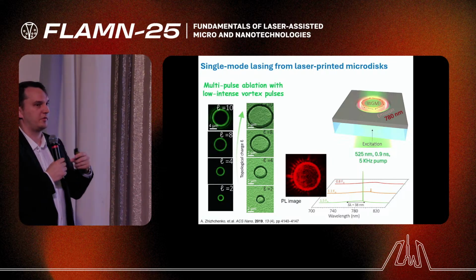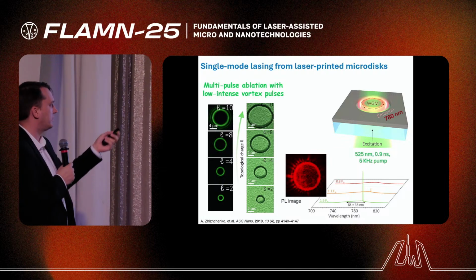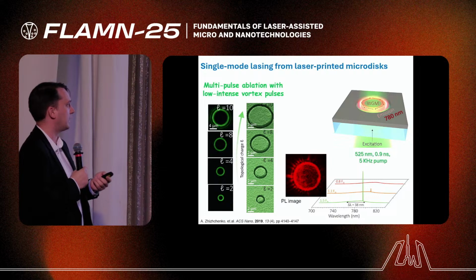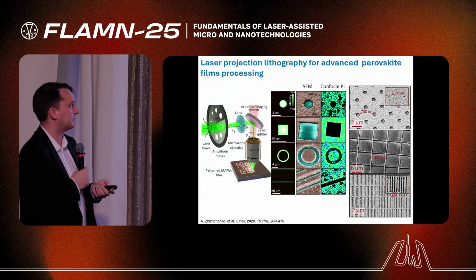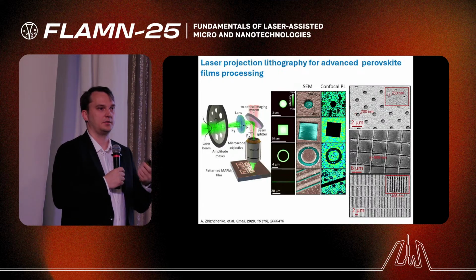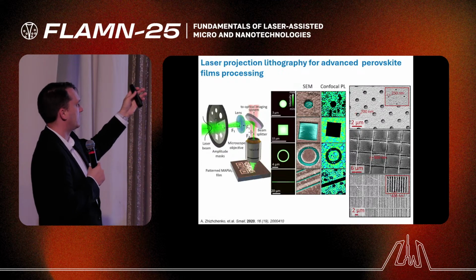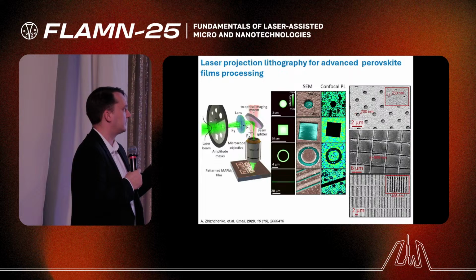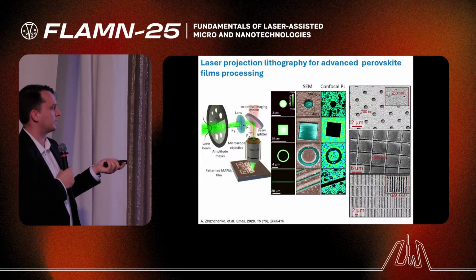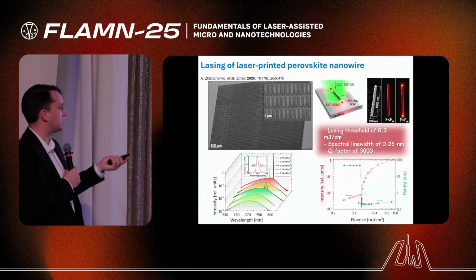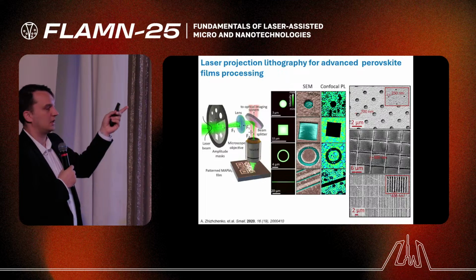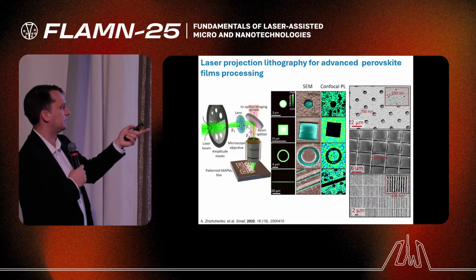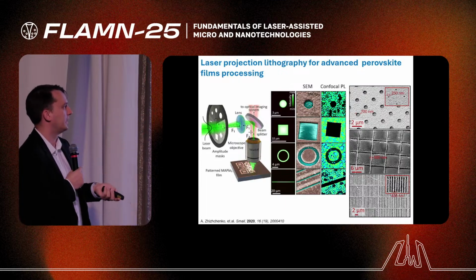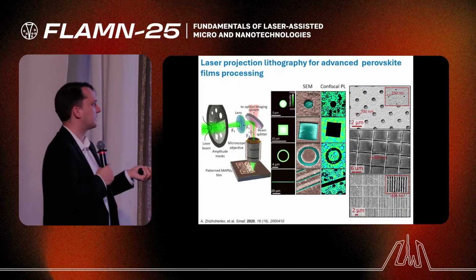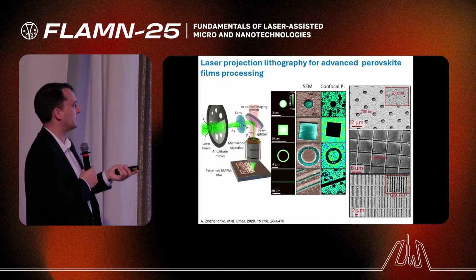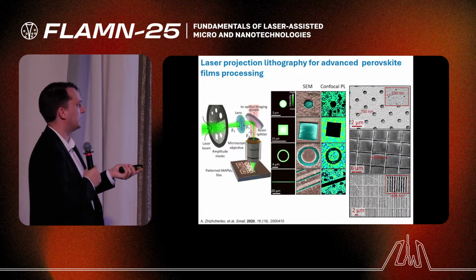Again, after the removal of material, light emission is still there for the remaining perovskite because of high defect tolerance. And projection lithography, femtosecond lithography, allows us to create different patterns. We can project different shapes of light beam and then form different structures like gratings, nanoholes, and so on. And you see from this photoluminescence confocal mapping that the luminescence of the remaining material is still the same as from the film around. So this is a clear demonstration that perovskite still emits light very well after laser ablation.